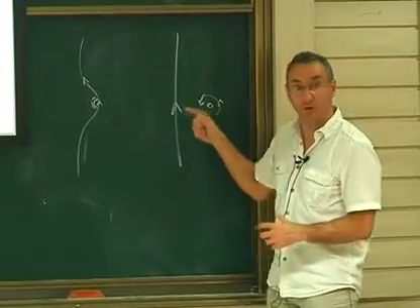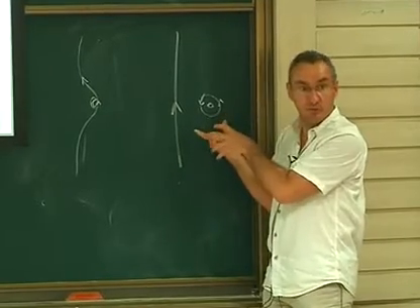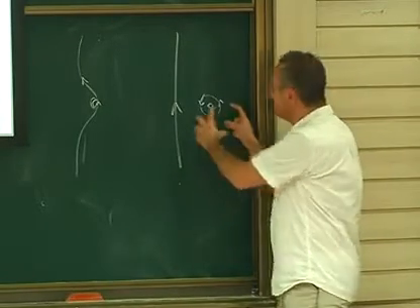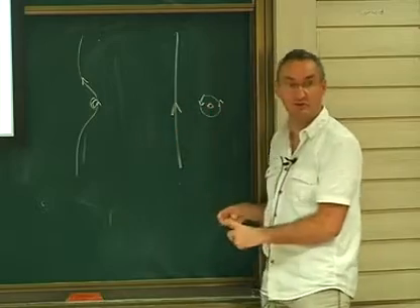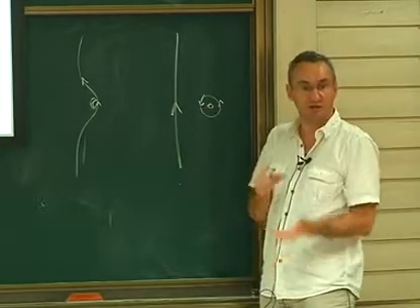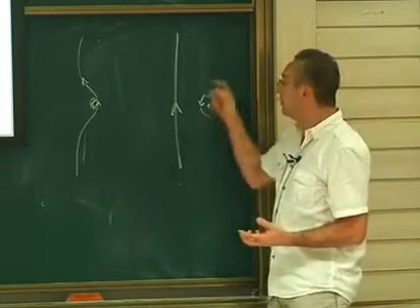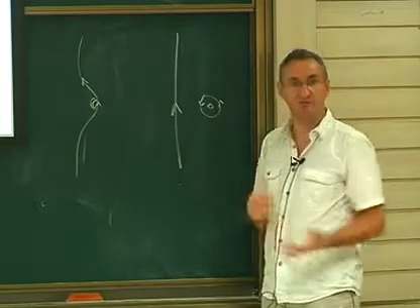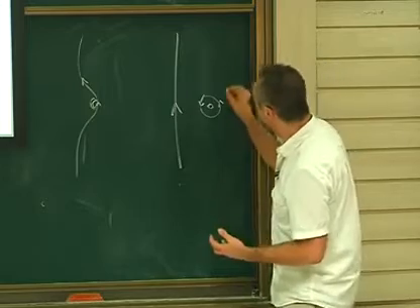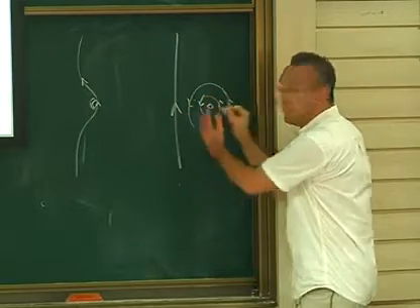This mechanism, or one mechanism, will be very strong for the particle. If this is a shearable particle, it will be very easy to shear, just because those loops want to shear it naturally. Because of the applied stress, it's even worse: you apply stress toward the shearing of the loop, just because of the line orientation. So this Orowan mechanism is very important for the shearing process of the particle. And if you have a second loop deposited, it's even worse, because you have a pile-up effect.